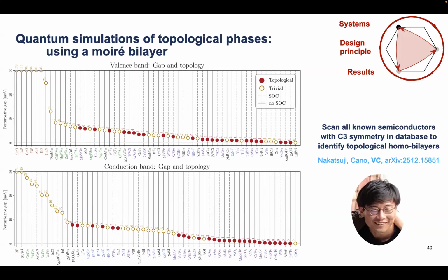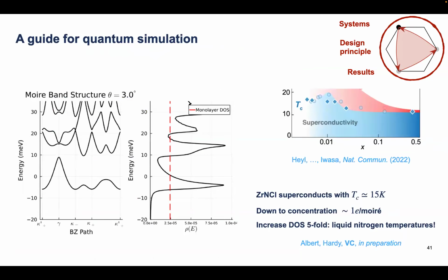Okay, and this list, you can actually learn a lot from it. So if you wanted to quantum simulate topological phases, you would go for materials that have a strong topological gap. Okay, but you could also say, can I look at something related to superconductivity? Then you go through the list here and you look for superconductors, and there's one right here, zirconium nitride chloride, which has a large enough gap. And by opening the gap, you increase the density of states compared to the monolayer, by about a factor of 4 for that material. And so you could increase Tc by a factor of 4. Tc in the monolayer material is already something like 13 or 15 Kelvin. So increasing it by a factor of 4 would actually put you in the strong coupling limit, where the Fermi energy and Tc would be comparable. This is heuristic, but we started looking into it.